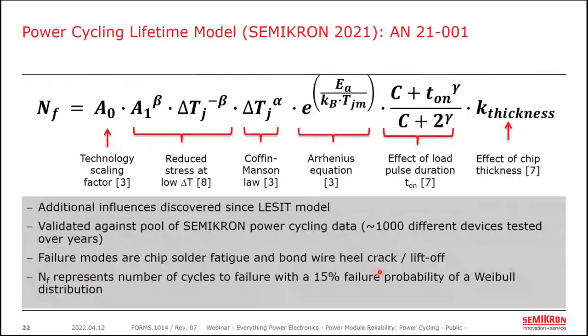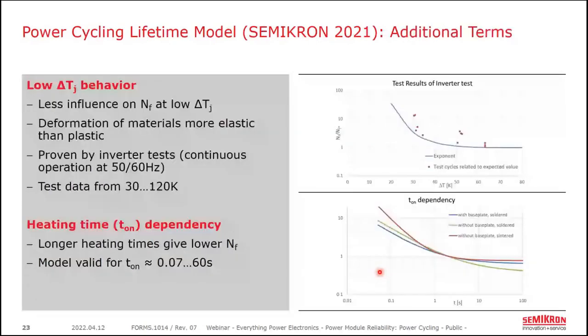You try and put in the higher on times, and you will see, based on this T on dependency, that we get a flat line in the model, depending on the type of module you have, after anywhere between 10 and 100 seconds. So that's definitely a realm that deserves more research. Mm-hmm. Okay. I get one question down and three more come.